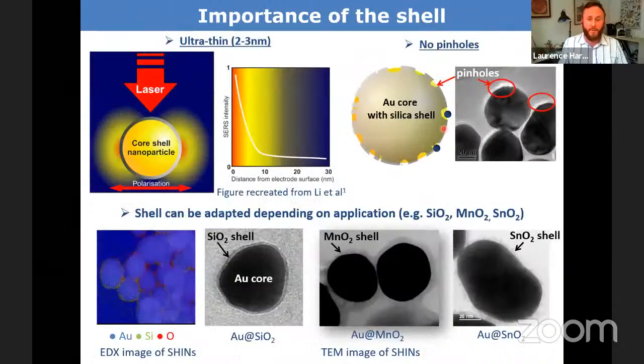So the shell that you put on your gold nanoparticle is extremely important. You don't want it too thin, because then you run the risk of these pinholes. And then all you would do is measure the Raman signal of any surface adsorbates on the gold, which is not really what you want. You want to just measure on the electrode surface.